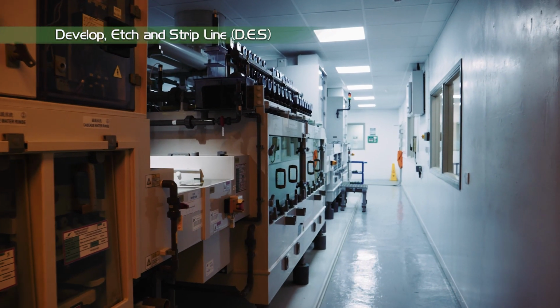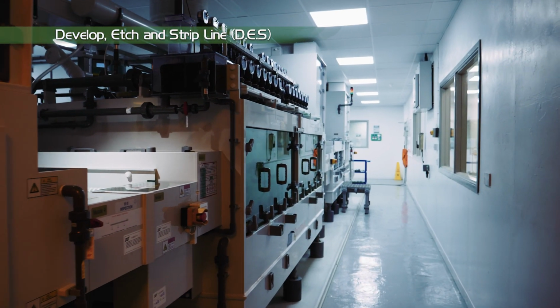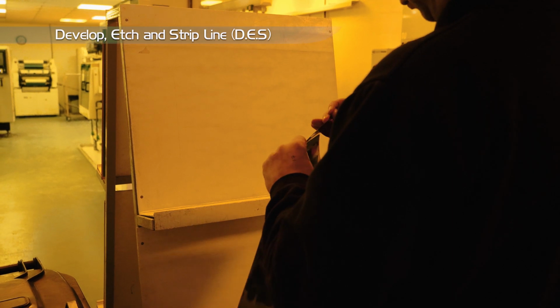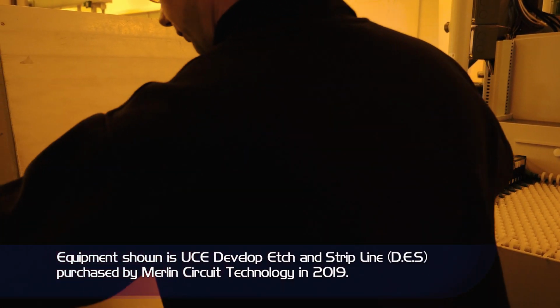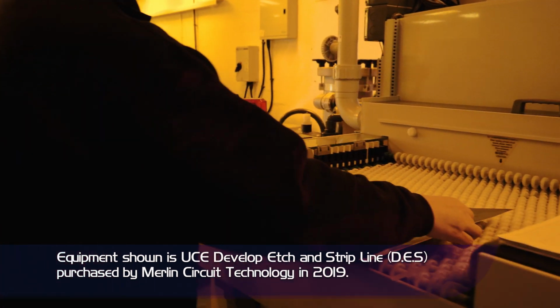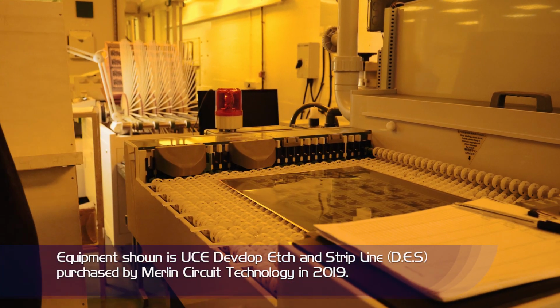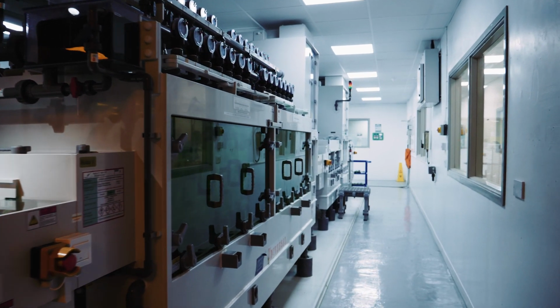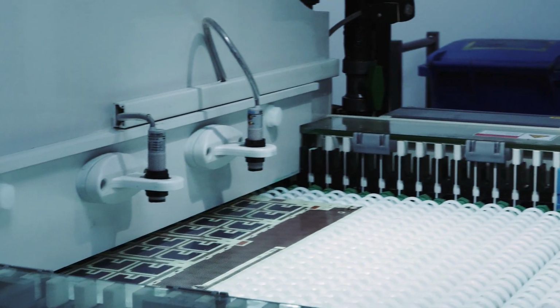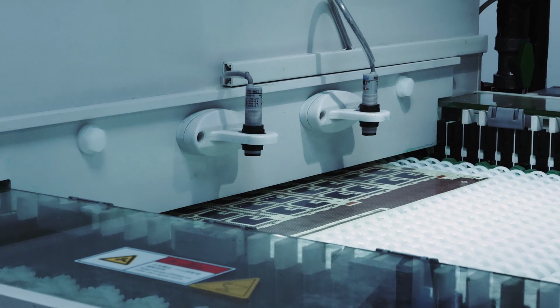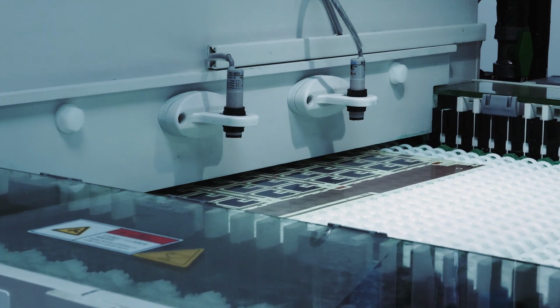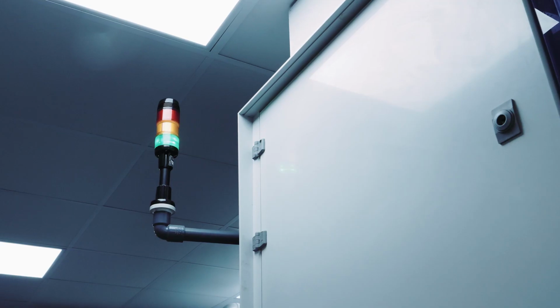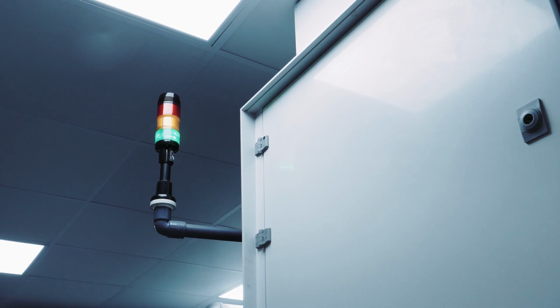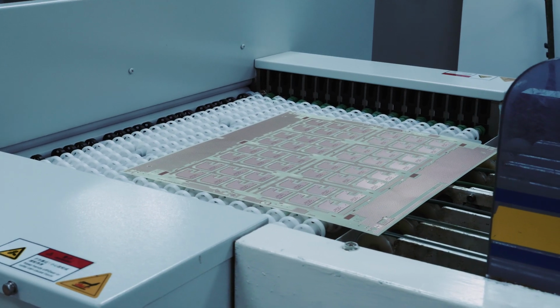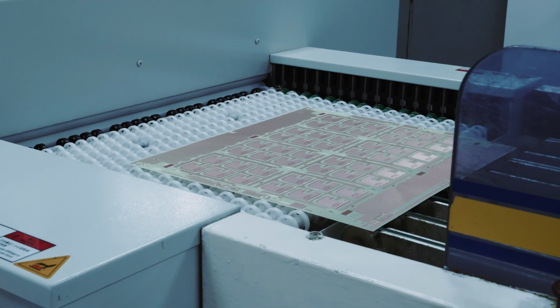The DES machine, standing for Develop, Etch, Strip. Firstly, the operator removes the protective mylar coating before loading into the developer section of the DES. This removes any resist that hasn't been exposed with UV light. The board then passes through the etch stage, which chemically removes the copper. Finally, the mask that has been UV cured and has stopped the etch from attacking the copper is removed in the stripping section of the line.